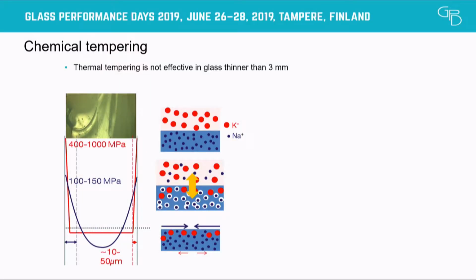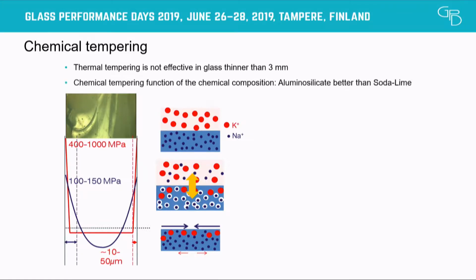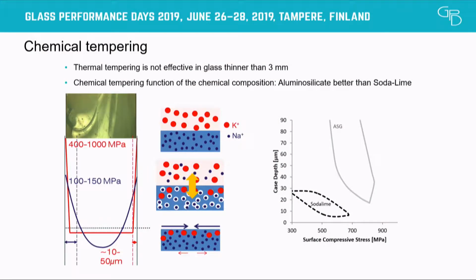And that's also another problem: thermal tempering will not be effective in glass thinner than 3 millimeters. So when we are talking about thin glass and we need to strengthen it, then chemical tempering is the protocol of choice. And if we talk about increasing the depth of layer, an aluminosilicate glass does much better than soda-lime glass. Just to give you an idea in this graph, if you compare soda-lime glass with aluminosilicate glass, you can see the potential case depth that you can build during a chemical tempering cycle against the surface compression that is generated during this cycle.